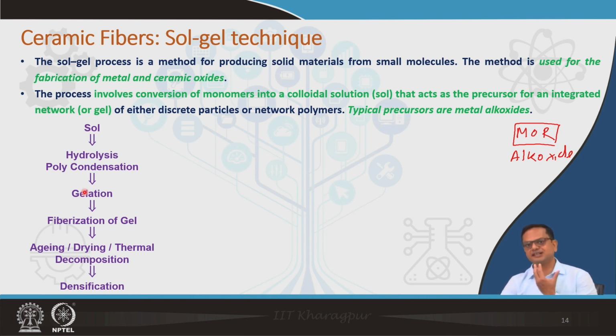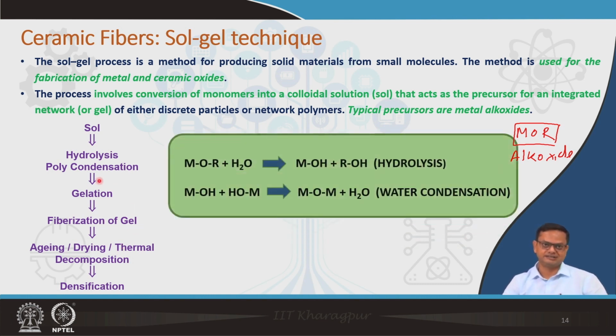Okay. Gel is basically a viscous material, and once you get this gel, you make fiber out of it. Remember, this gel is yet to form the oxide, it is not the oxide. This gel goes through a calcination process of aging, drying or thermal decomposition, and that ultimately leads to formation of the oxide. For example, here this is MOR, and you go through a hydrolysis process. So, you get MOH and ROH, and two MOH molecules ultimately will give you MOM and H2O, and that is water condensation.